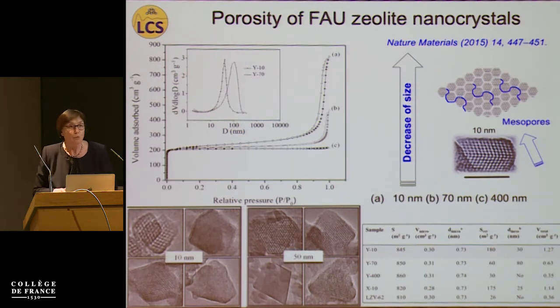A similar approach was applied toward preparation of faujasite nanocrystals. As you know, faujasite is an extremely important material, especially for FCC catalysts. Therefore, here the task was to synthesize ultra-small faujasite nanoparticles in the presence of sodium hydroxide only. As a result, we obtain crystals which are individual, not agglomerated, and these crystals exhibit extremely high microporosity.